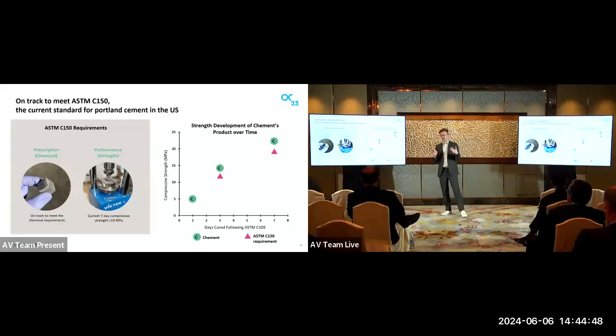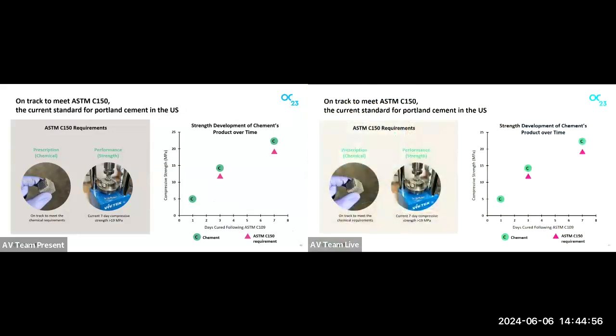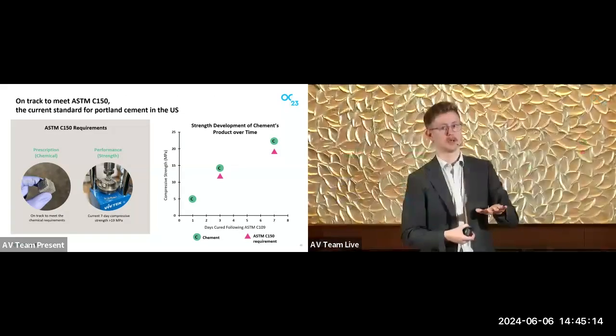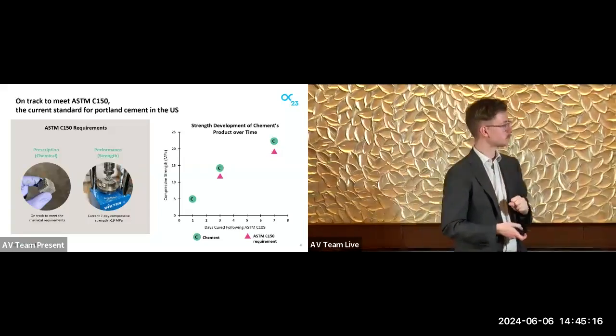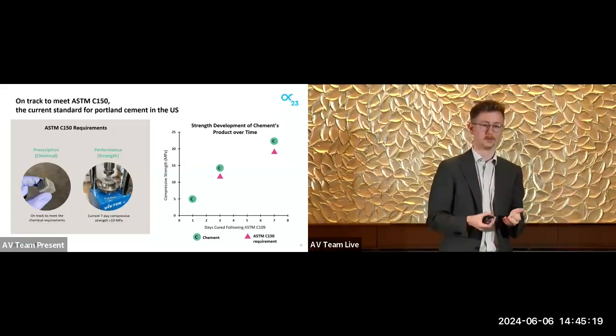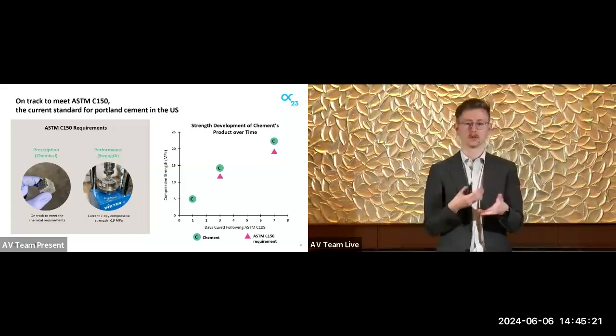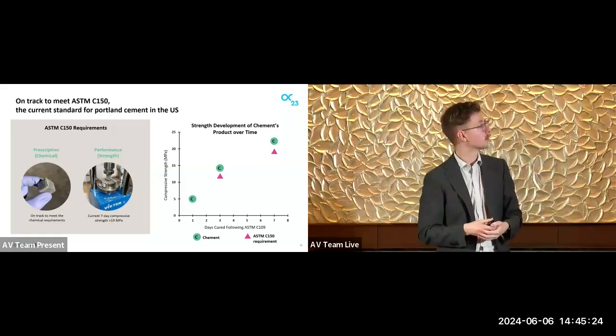The benefit of electrochemistry is that we can actually validate the technology even at a small scale. And from our testing of smaller cubes, we've been able to demonstrate that at least according to the American ASTM standard, our strength development is exceeding the minimum requirements today. We think we can actually keep increasing that to be even a faster developing strength material while still keeping that calcium content much lower than conventional clinker. And we're on track to make sure we meet all of the chemical requirements for that cement as well.